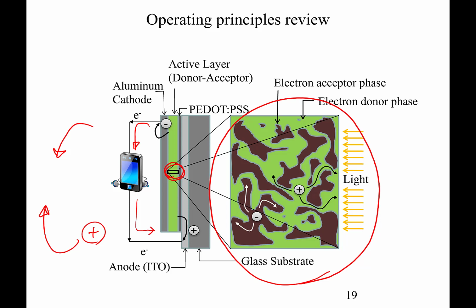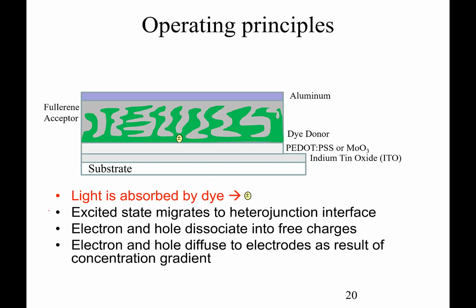Let me zoom in a little bit more, and I'll tell you about the 4 steps, these operating principles for these devices. So first of all, we need to have a transparent substrate, and this is our transparent substrate in here. It's coated with what has to be a transparent conductor, and this is typically indium tin oxide. The problem with this is indium is going to run out eventually, so that's important to find a replacement in the long term.